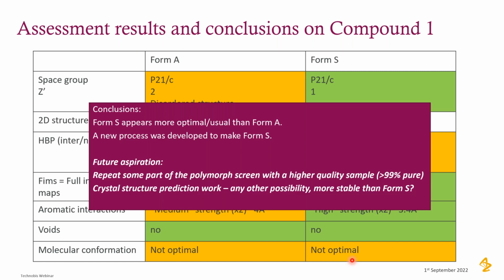So because we know that Form S appears more optimal and usual than Form A, we basically focus our attention to develop a process to make Form S. And in the background, we also work a bit more to review the polymorph screen and make sure that it was done with a higher quality sample and we haven't missed any key experiments. We also did some crystal structure prediction work to see if there was any other possibility more stable than Form S. So that's really driving basically our risk assessment.